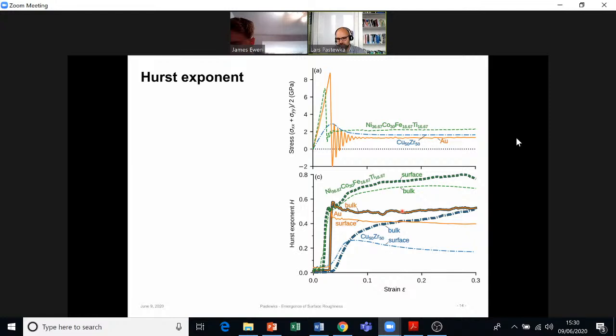And indeed, if we look at the structure that forms, if you take a visual image of the surface structure, it seems to be sort of imprinted on the system at the point where the material yields, and then it evolves further. But the main structure seems to remain the same. So we're currently trying to quantify this by looking at cross correlations between the topography maps obtained at different values of the strain. Okay, thank you very much.